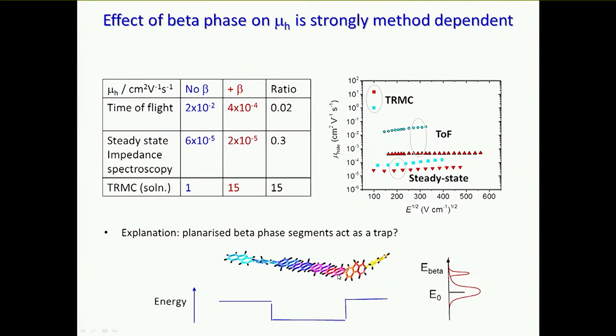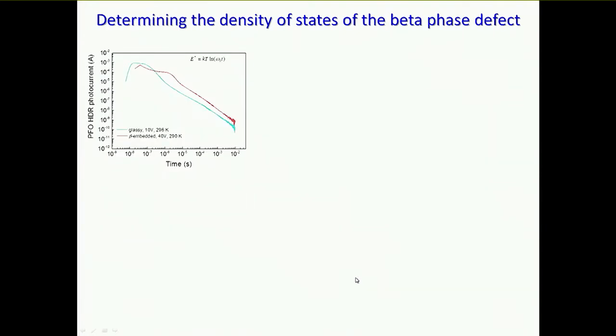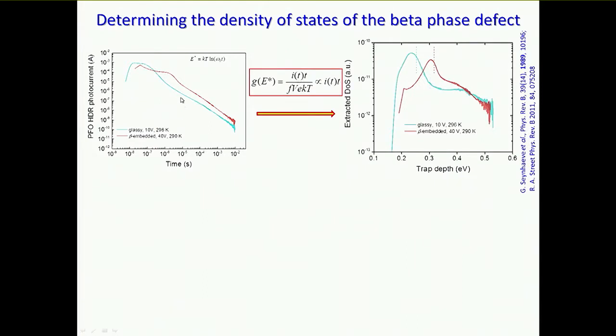And if it acts like a trap, then it ought to be visible if we were able to probe the density of states. So we tried to do that with 2 different methods. In one of them, we took our transient photocurrents to a very large dynamic range. And in that limit, you can interpret your photocurrent transient as a density of states. So the response at long times ought to reflect the rate at which charge carriers are released from states in the gap of this material. And from that, we could extract a density of states. Doing that, we could see that when the beta phase was present, it introduced some extra feature below the transport edge relative to the glassy material. So it seemed to introduce a feature in the gap that was more or less what we expected.